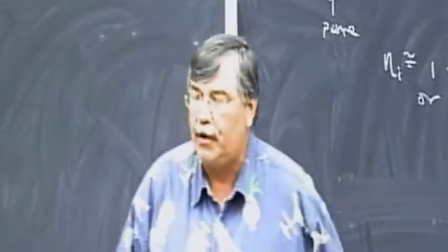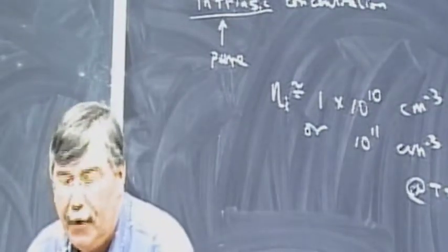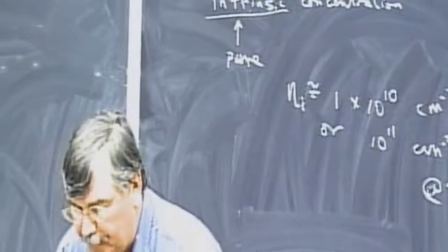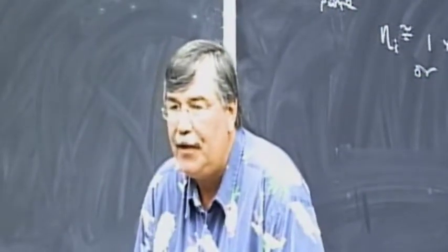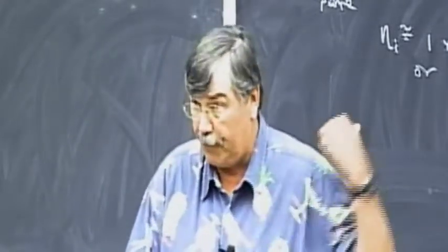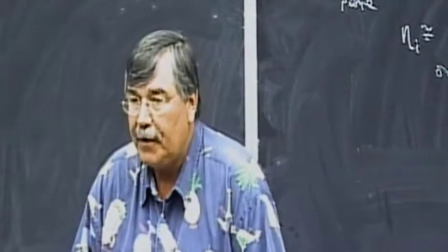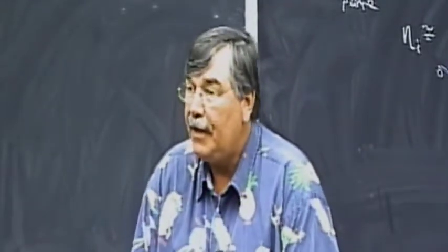So the higher up in temperature you go, the more likely it is that we're going to have created free electrons and left behind the so-called holes. All right? So this is the concentration for pure silicon. The reason we don't spend much time actually talking about pure silicon is even a very, very small concentration of any kind of impurities tends to overwhelm the concentration that we would have had in pure silicon. So typically in silicon, we intentionally add impurities of either 2 types in order to control the concentration of the electrons or holes that are in the material.